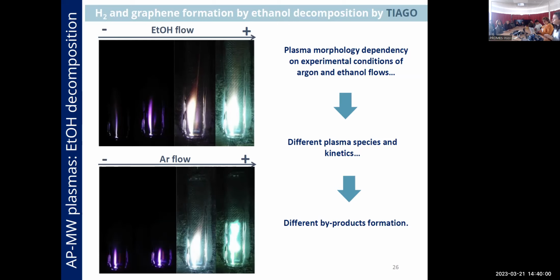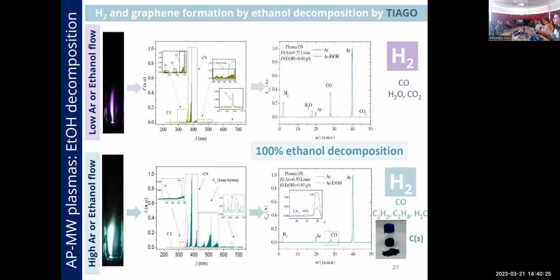This is something totally different from what happened with the surface wave discharge, where the plasma was all the time, let's say, green. Here we have different colors of our plasma, which means that we have different plasma kinetics depending on the experimental conditions, and these conditions will promote different byproduct formation. So here we have a summary of what is happening with low argon or ethanol flow, where the plasma looks more purple, and in the bottom part, a picture of our plasma with high argon or ethanol flow, where the plasma is green.